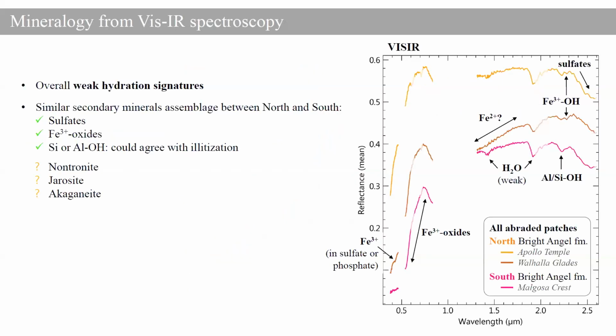So with this IR spectroscopy, what we saw was relatively similar between the south and the north, with some slight variations. We have relatively weak hydration bands. We have some drop of reflectance past 2.3 micron, likely related to sulfates. And the spectra also show a 2.2 micron, so aluminum or silica OH band, and that seems to be deeper in the south, so here in this pink spectrum. And this could agree with illitization, because illites also have a 2.2 micron band as well.